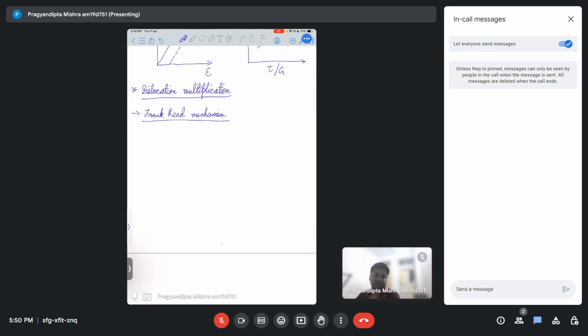So let's assume that we have a dislocation like this, which is moving in some direction due to the presence of some stress tau, and it hits two pins. Now these pins could be anything. It could be due to solute, precipitate, dispersoids, other dislocations, or grain boundary. There are two pins which are not allowing the dislocation to move forward anymore.